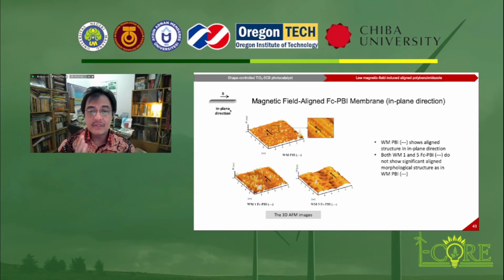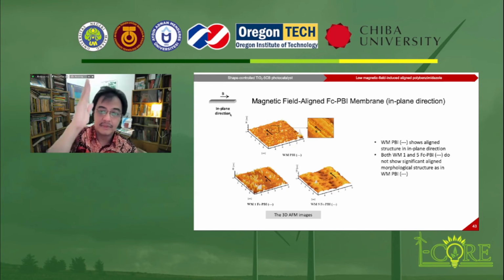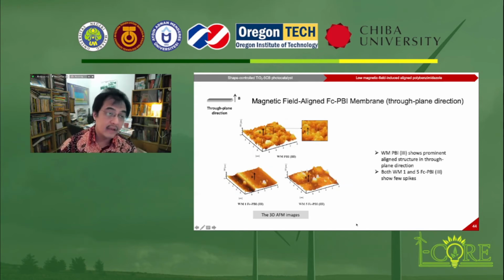And the effect of the alignment in the through plane direction was also shown by the AFM. We can see that small spikes are uniformly and densely distributed on the membrane surface, which indicates the successful alignment of the polymer microstructure even at low ferrocene content. Please remember that ferrocene has iron, so these spikes reflect the content of the iron in the ferrocene. It can align with the magnetic field.